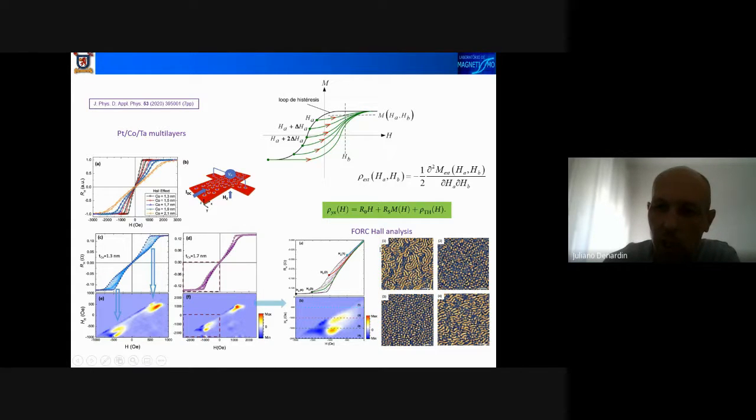And we did a magnetic force microscopy on the sample for different reversal fields. That means we come to HR1, that is minus 500 Oersted, and come back to zero field, and measure the MFM, and we observe these stripe domains.